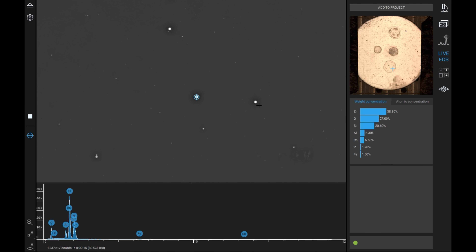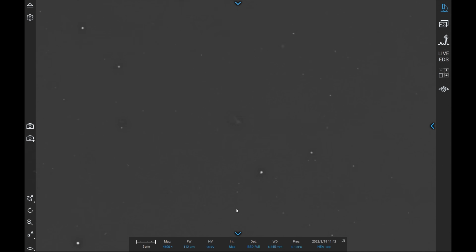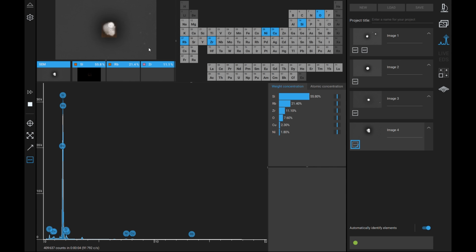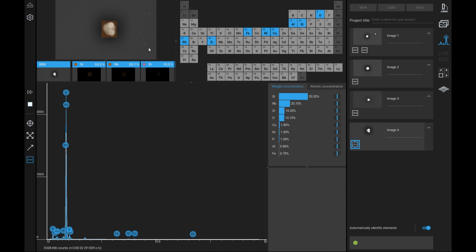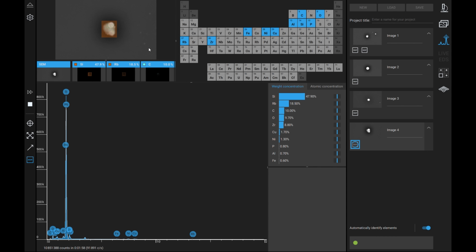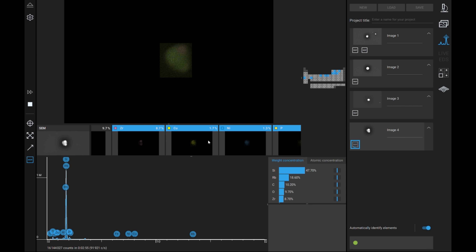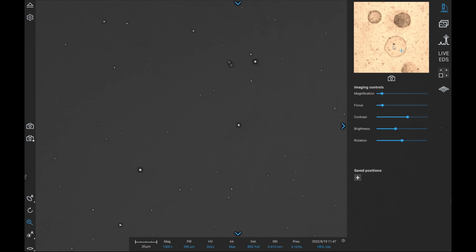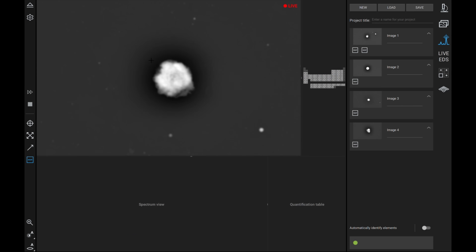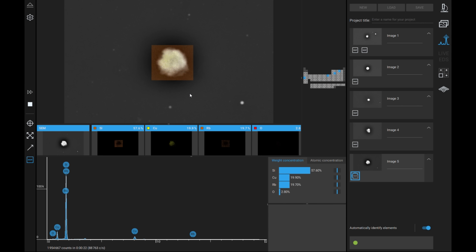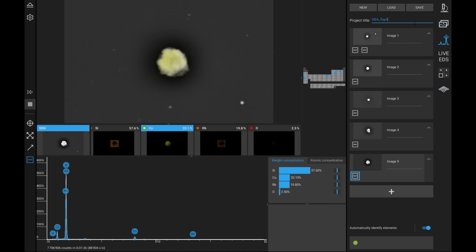Furthermore, the smaller the particles, the harder they are to analyze because there is a resolution limit to the EDS detector which is generating these element spectra. So I tried to focus on particles that were greater than about 500 nanometers, because below that I don't really trust the resolution of this system — which is unfortunate because likely the best candidates are the really small nanoparticles, from 15 to 100 nanometers. But we just can't look at them on my machine.